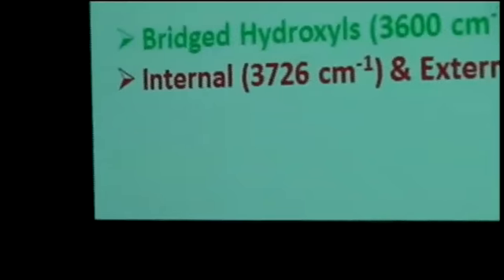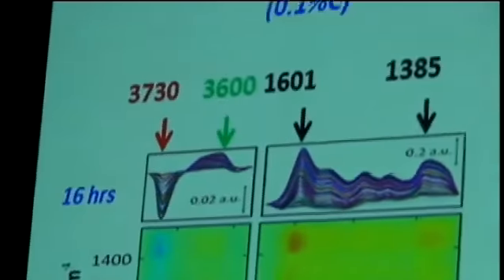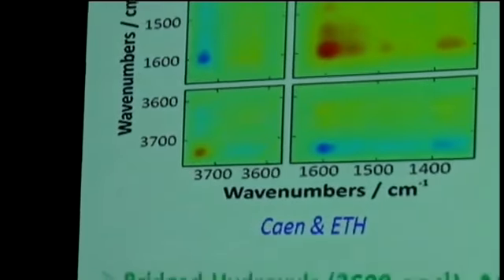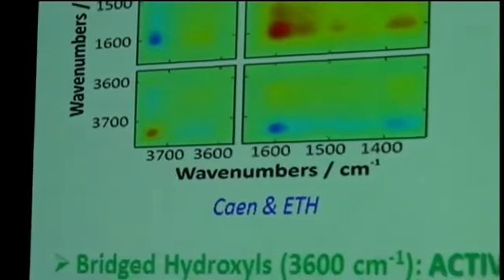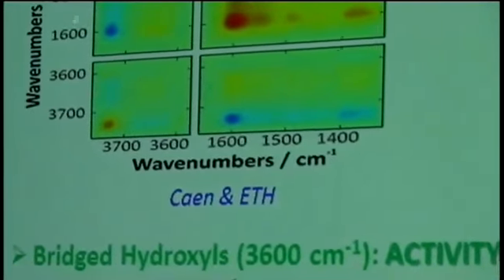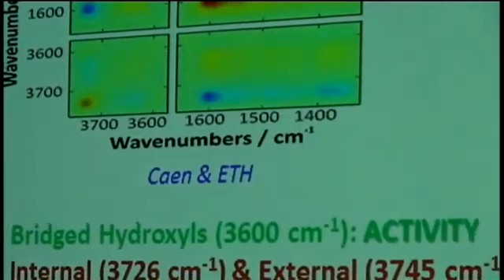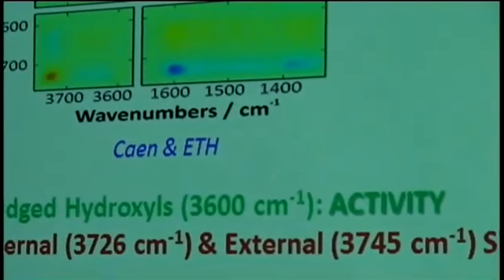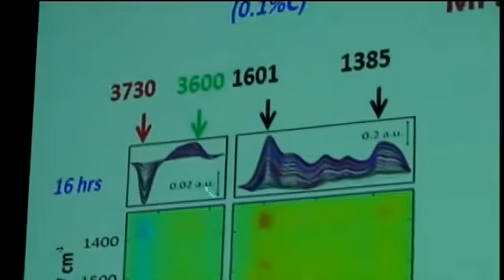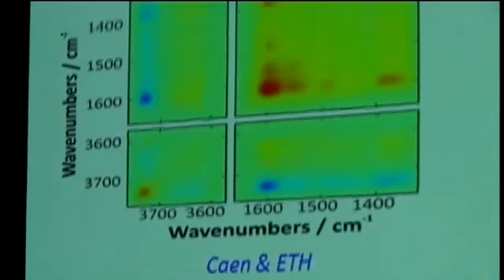I like this slide because we were looking by operando spectroscopy at the coking during a reaction where in fact not a lot of coke is happening. It is orthoxylene isomerization on ZSM-5, and after one night there is barely 0.1% of coke. By operando spectroscopy and by correlating the active sites, the silanols and the species on the surface, we were able to show that the active sites are barely touched by the small amount of coke that is present, and the coke is located on the silanols.